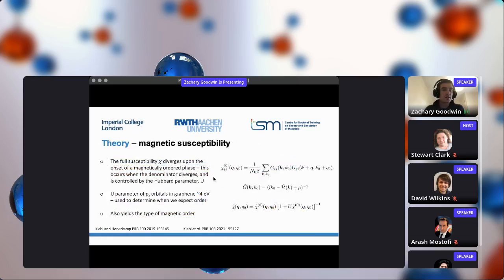Right, so now we want to investigate the role of these electron interactions on the magnetic properties of the system, and even performing a mean field analysis like the one I've just presented for Hartree theory, with a Hubbard interaction too, is prohibitively expensive. So instead we decided to calculate the magnetic susceptibility of the system. When the susceptibility diverges, it indicates the onset of magnetic order. And it can tell us the critical on-site Hubbard parameter required for magnetic order to occur.